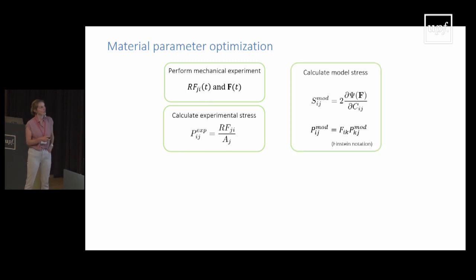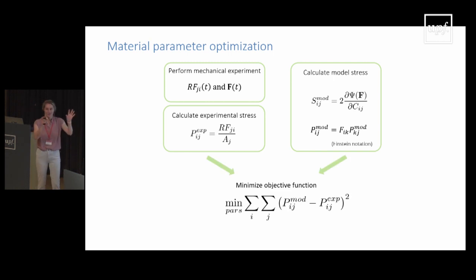And on the other hand, you have your model, which in biomechanics we often represent using a strain energy density function. So with that strain energy density function and information about the deformation gradient, we can then calculate our second Piola-Kirchhoff stress, which we can then transform to the first Piola-Kirchhoff stress. And once we've done all the math correctly, we can minimize an objective function.